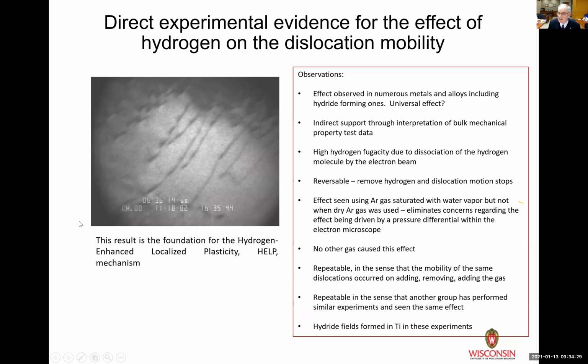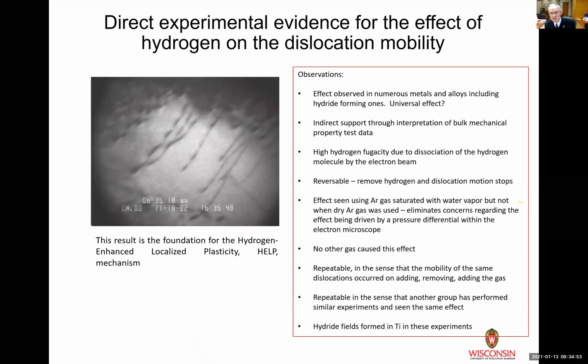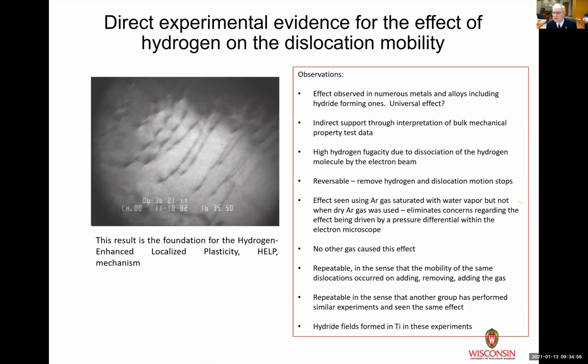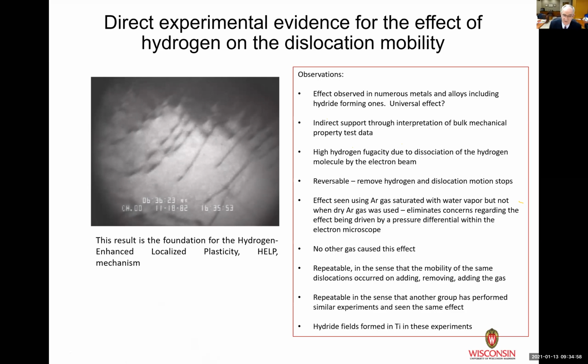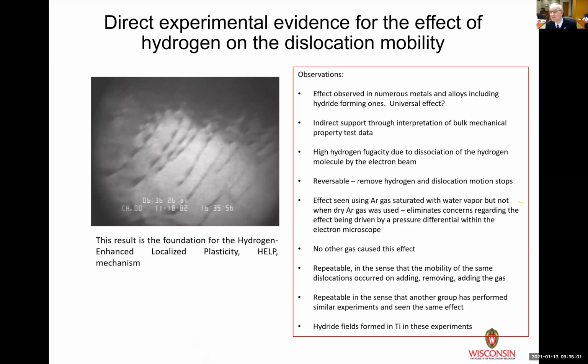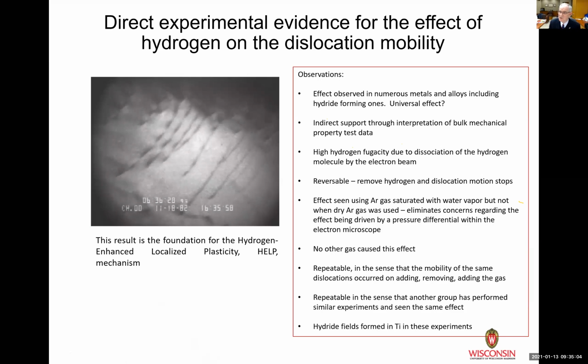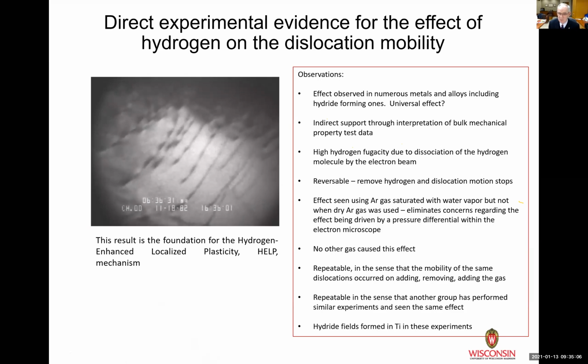And we allowed that hydrogen to interact with the metal. Now, one of the things that does happen is that the electron beam comes down and interacts with the hydrogen molecule. So you'll get atomic hydrogen. So we have high fugacities present at the sample surface. So I think we're pretty confident that we were injecting hydrogen into this sample. So what happens when we inject? You'll see the image degrade slightly, and then you'll see those long black lines just start moving. There is no increase in the applied load. It's all due to the presence of the gas in the sample.